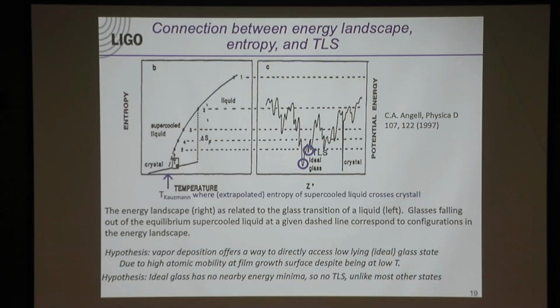my claim, and this is a speculation, if you go back to this energy landscape, is that for that lowest lying state, there are no nearby states, almost by definition. There are no nearby states, so of course there are no tunneling states. So by making this ideal glass, that is why I've made a low tunneling level state system. So the hypothesis is that while liquid quenching, you always fall out of equilibrium. It's very hard to reach a low-lying state.